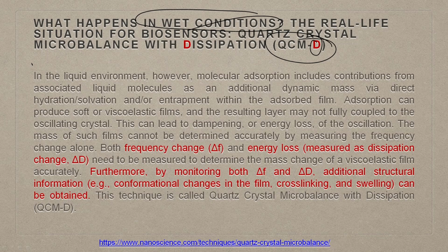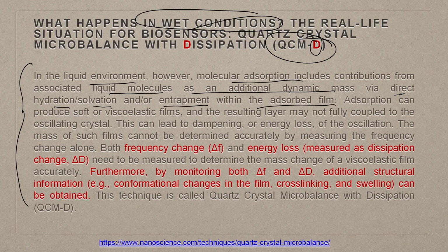Now, if you look at the slide, in the liquid environment, molecular adsorption includes contribution from associated liquid molecules as an additional dynamic mass via direct hydration, solvation and entrapment within the adsorbed film. Adsorption can produce a soft viscoelastic film.